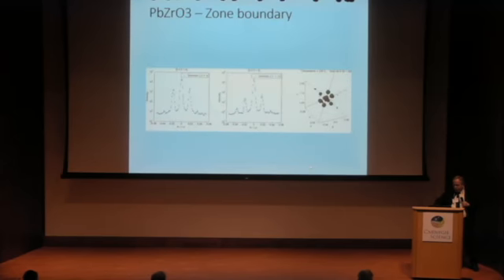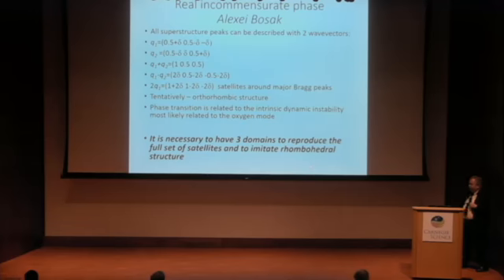But at the moment, I'm more interested in the zone boundary, because nobody has really considered the zone boundary situation in detail. As I told, we have a complicated structure of superstructure peaks that couldn't be described by the previously proposed picture of antiphase domains. So what we can do, in reality, is consider that we have an incommensurate structure described by two rays of the same wave vector star. And then, using the combination of these two rays, we can describe the satellites. Now, the main M point becomes a second order effect. And it's very reasonable because the total intensity of the satellites is much higher than the intensity at the M point.